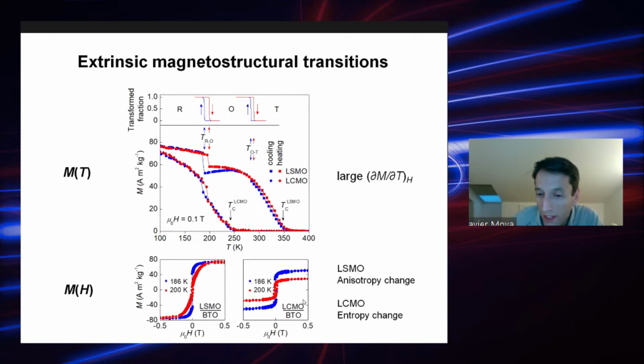In the case of LCMO, you can see that there is a change in magnetization across the transition, so this will point to an entropy change. Whereas in the case of LSMO, you can see that the total magnetization doesn't really change, but there is a change in anisotropy. And this points you in the direction of having good magnetocaloric effects.